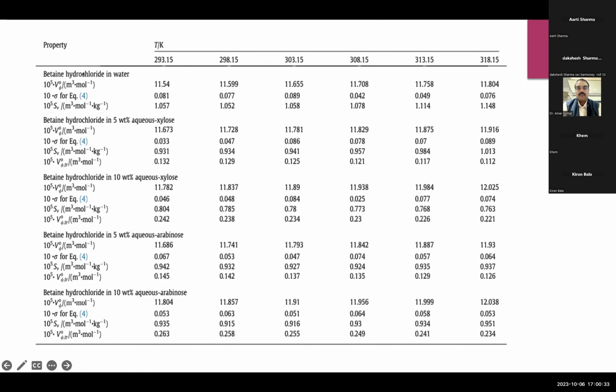Now, these are some properties of the limiting apparent molar volume, which is denoted by V phi naught. Then this is sigma, the standard deviation, and this is SV. The limiting apparent molar volume is the molar volume at infinite dilution. At infinite dilution there are no solute-solute interactions present, only solute-solvent interactions. As you can see, comparing water, 5% xylose solution and 10% xylose solution, on increasing the concentration these values were found to increase. As these values increase, the solute-solvent interactions are also increasing.